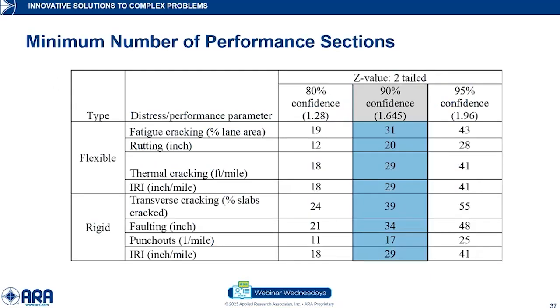We've got the bias, the standard deviation, and we're going to go with a 90% confidence level, which is probably the conventional one to use in most cases. And then you have there in that column the minimum number of sections you need for each one of those distress models. Roughly speaking, most of them require about 30 or more. There's an exception for rutting and punchouts where you can get by with less. But you can see here where you have to balance the confidence level with practicality.